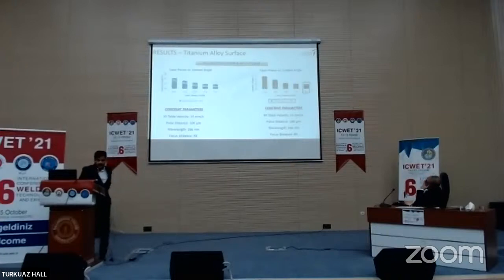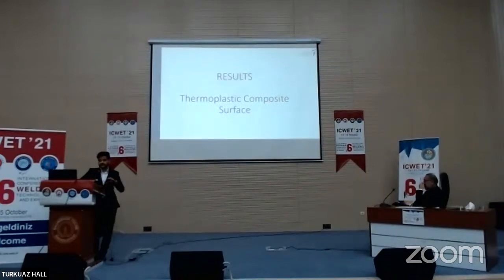Then we also optimized the power and the focus distance during this study. As you can see, we applied the same power at different focus distances. If you look at this graph on the left side, you see that if you increase the power, your surface is getting more activated when you compare the contact angle results. And if you change the focus distance from 9x to 8x, you see the activation increasing also by decreasing the contact angle. Therefore, when we analyze these results, we obtain the minimum contact angle at 255 milliwatts and 8x focus distance.